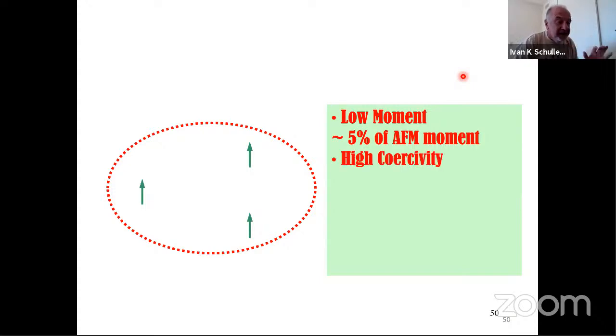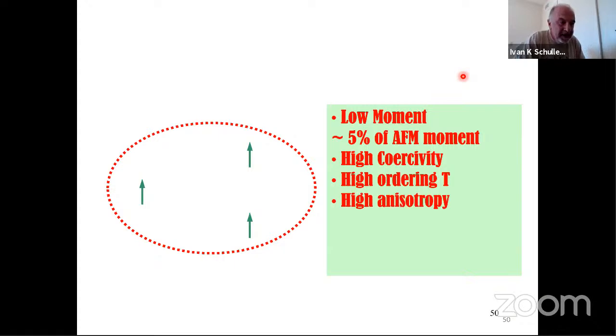They have a high coercivity because in order to rotate the green spin, you not only have to rotate the green spin, but you have to rotate the whole background that there is around it. They have a very high ordering temperature because the ordering temperature of those green spins is not what it would be for three spins, it would be the ordering temperature of the antiferromagnet. It has a very high anisotropy because again, the anisotropy is given by the anisotropy of the antiferromagnet.